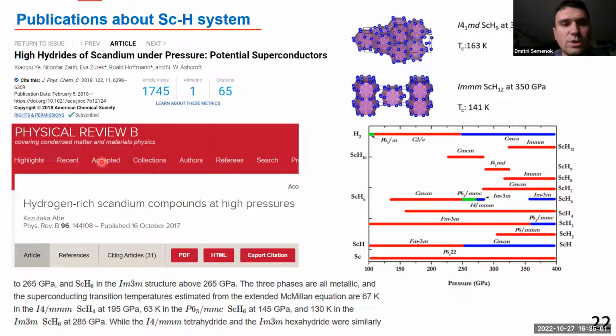There are several publications already. For example, Eva Zurek with Roald Hoffmann predicted the formation of a lot of scandium hydrides. It's a very rich system. There is scandium H3, H2, H1, H4, and a lot of higher polyhydrides such as scandium H6, 7, 8, 9, and 12, and probably even higher hydrides. Most of them are good superconductors, and the maximum TC is close to 160 kelvins. So it's something we expect from theory, our expectations.